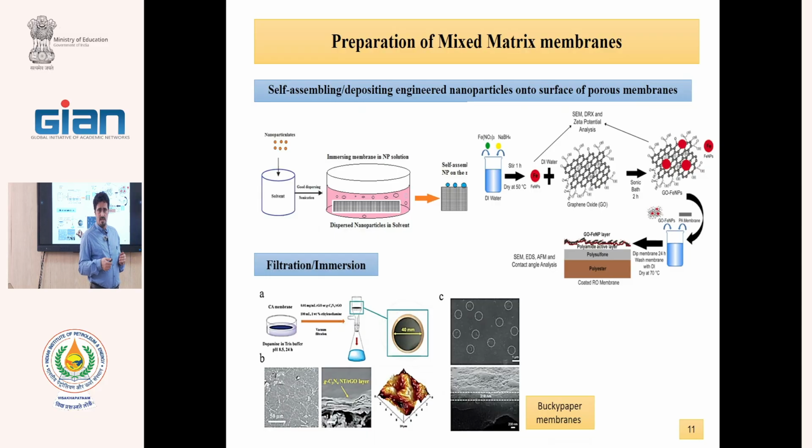In some cases, for carbon-based materials like carbon nanotube and graphene, the membrane has good stability. But after 10 or 20 days, this membrane type is also detached, because this technique is also physical and not a good attachment. But it is better than the top one because we use pressure for coating of the layer.